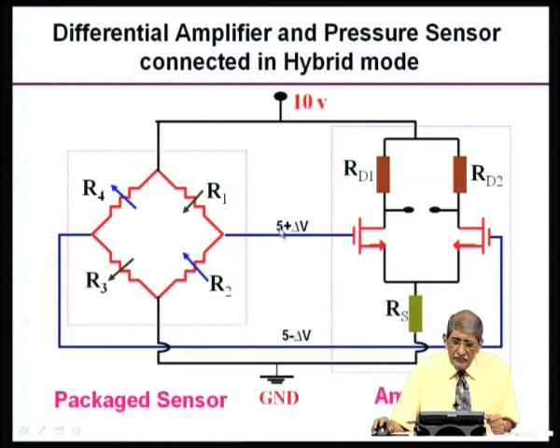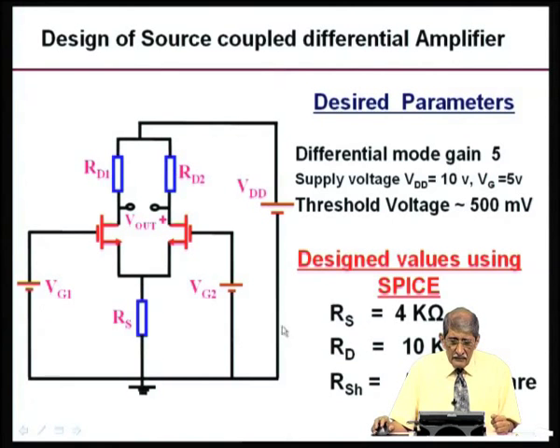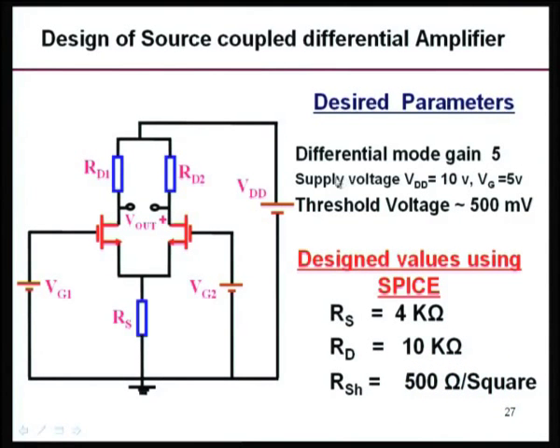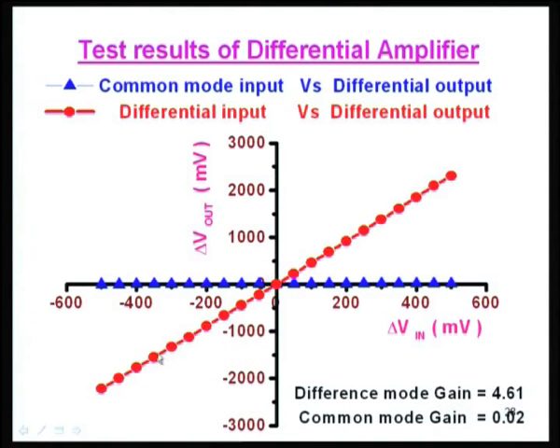If the inputs are 5 plus 0.1 volts and 5 minus 0.1 volts, 0.2 volts will be the differential input, and that will be amplified by the differential gain. If you have a gain of 5, the output will be 1 volt. So, you can amplify that depending upon the gain, which is decided by these resistor values. I am not getting into the design of this in this presentation. Okay. So, this is designed with certain values of resistors to get a gain of 5 using a simulator, and you can see that the differential input gets amplified, delta V output versus delta input is linear, the gain is about 4.6 for this device when it is fabricated, the design was about 5.